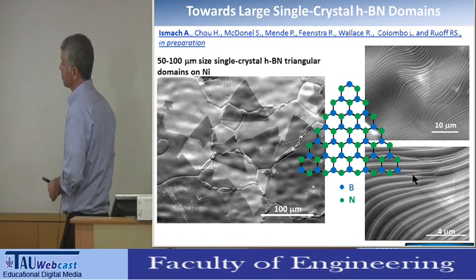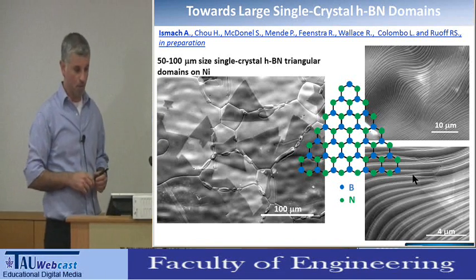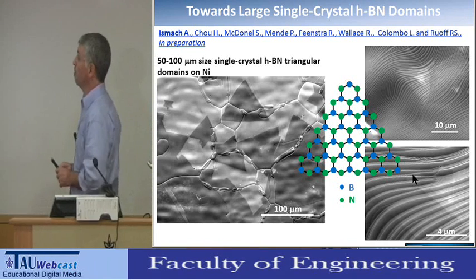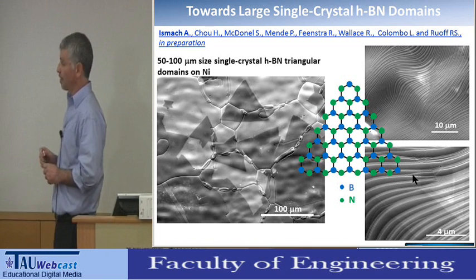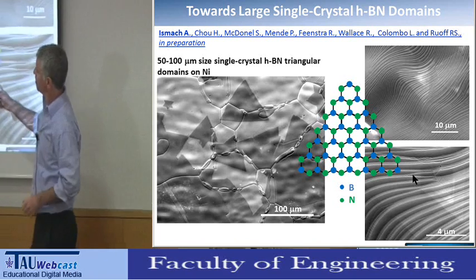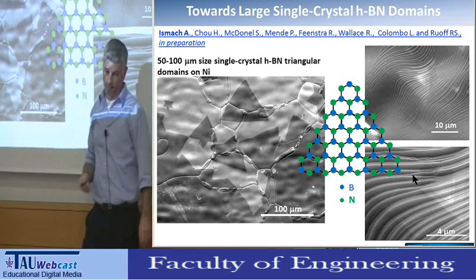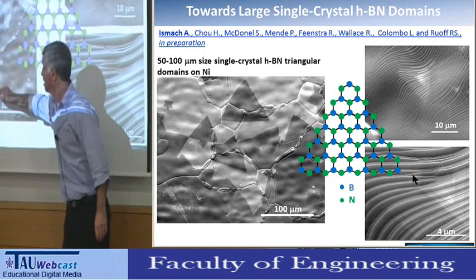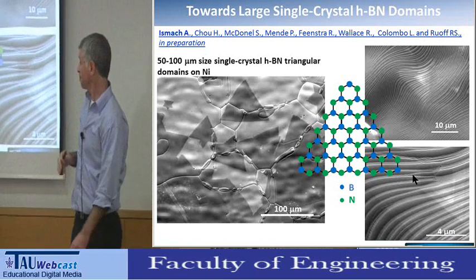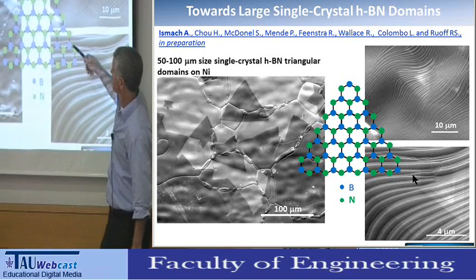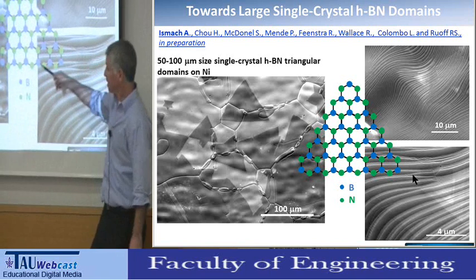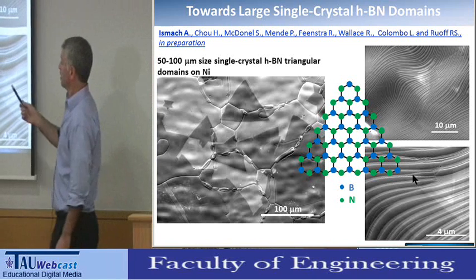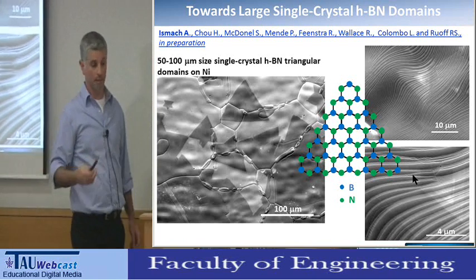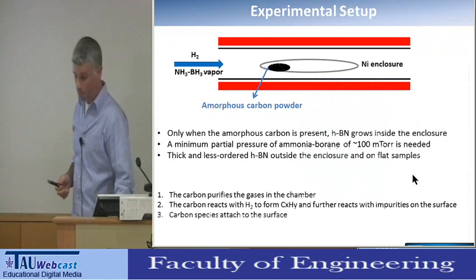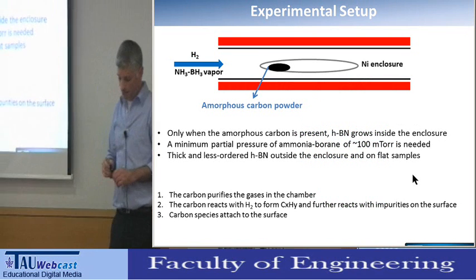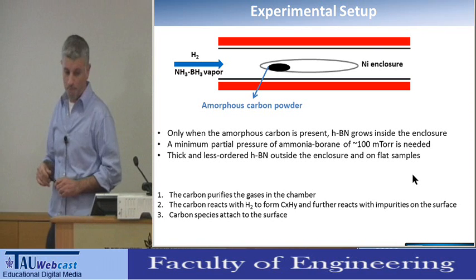But then we continued to grow HBN by different methodologies. Today, and I will show you in a minute how, we can synthesize very large single crystal domains of HBN, as you can see here. The triangular domains are HBN. The black areas are covered by HBN. The brighter are the exposed nickel. This is a schematic representation of an HBN triangle. This is based on theoretical reports showing that the N termination is just more stable than the boron termination. And the way that we do that, and we discovered that, I must say, by coincidence, is by using what we called in the group a nickel pocket.